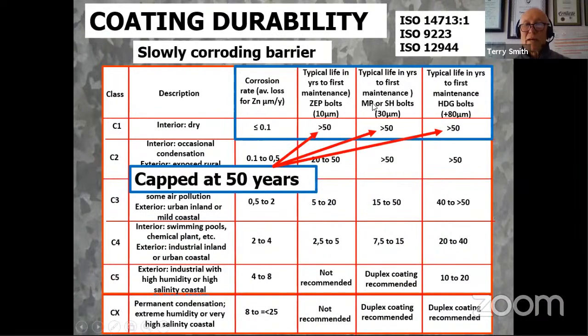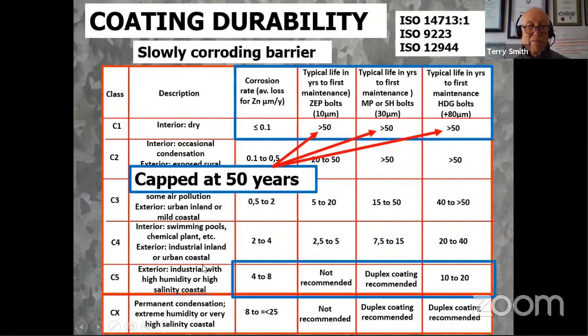The mechanical plated and Sheradized bolts are 30 microns, and the typical galvanized bolts are 80 microns. Just to be fair, if you look at C5, exterior industrial with high humidity and high salinity, it's about 4 to 8 microns of zinc loss per year. Not recommended with zinc electroplated bolts. Duplex coating is recommended for these 2 bolts, and with hot dip galvanized bolts of about 80 microns, you'll get about 10 to 20 years of life.